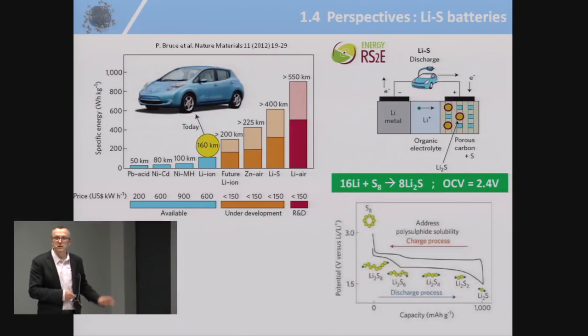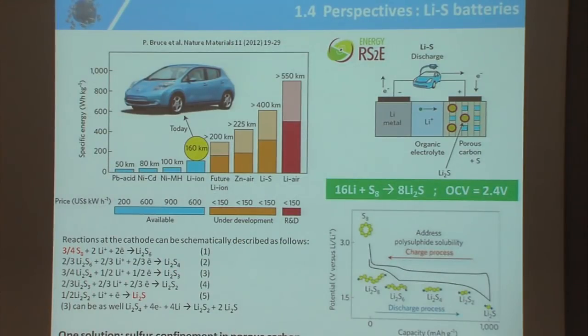That's the theory, because practically speaking, to move from this to this, you go through all these reaction steps. And you have 5 different steps, and you have 5 different problems to solve. Why? Because you form species here, sulfides, you see here. Some of the sulfides are soluble, some of the sulfides are insoluble, insulators, and then you have a lot of problems to tackle and to deal with. However, one solution to try to solve the issue is to, again, confine the sulfur into porous carbon, which has been done 2 years ago by a Canadian group in McGill University. These are very good results. And lithium sulfur battery starts to work today.